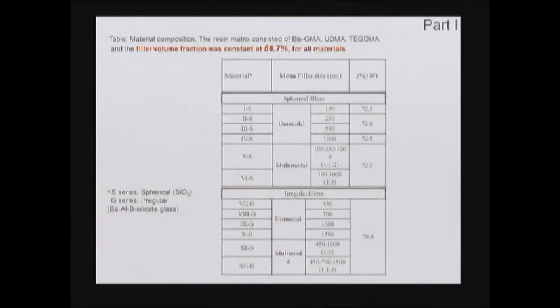Now, all of this research that I'm going to describe is done by using what we would call model composite materials. So these are experimental formulations that were formulated with a specific purpose, namely to know exactly what is in there so we can very systematically hit one parameter and we can study that parameter alone. So these ones, they were divided as spherical filler particles and irregular filler particles. The difference is that you can have different filler sizes, and you can have unimodal or multimodal approaches in there. They all have the same resin matrix, and they all have the same filler volume. So filler volume was about 56.7%, and in terms of weight, it roughly translates to about 72 for most of them there.